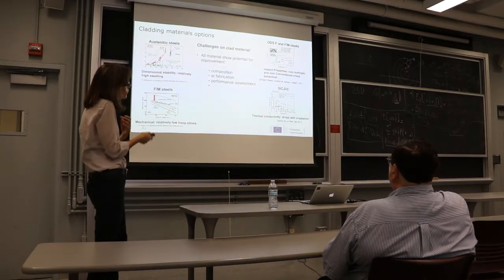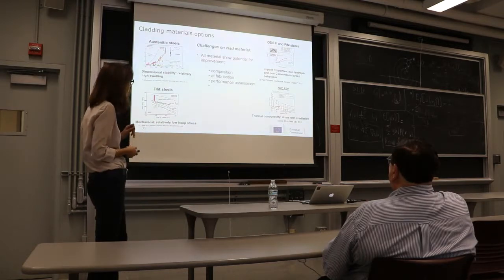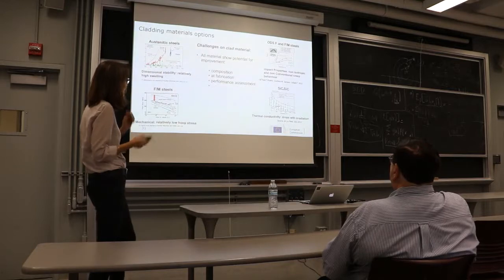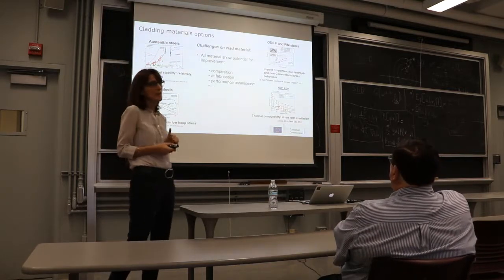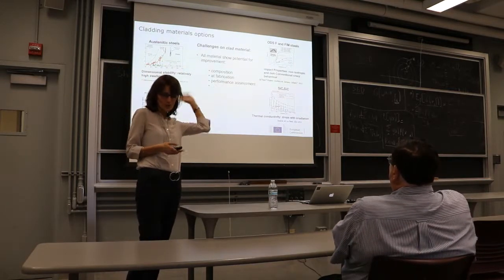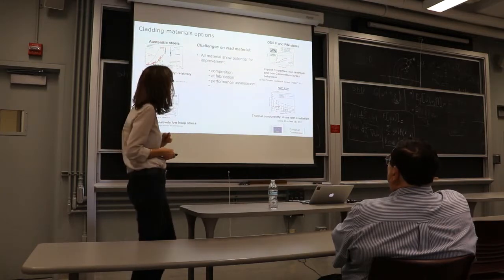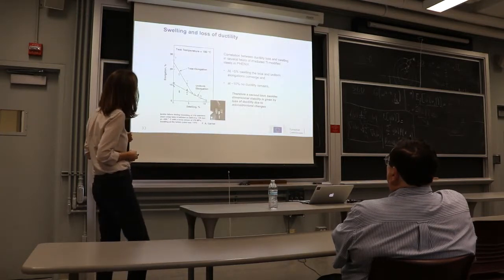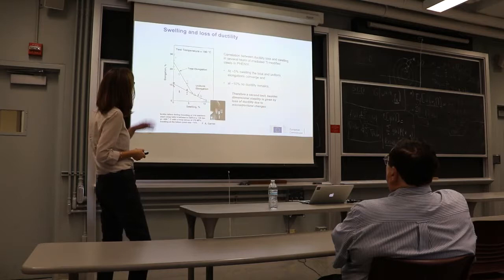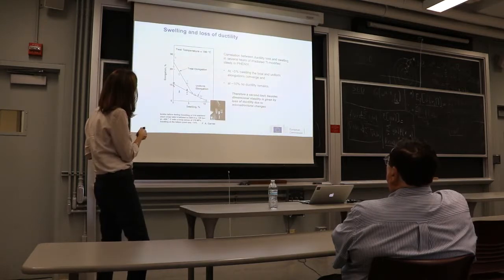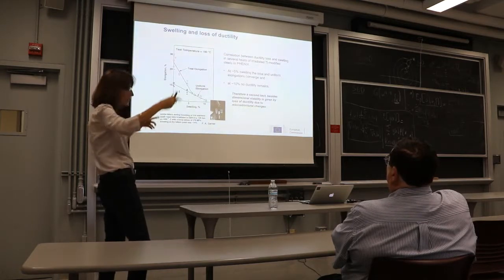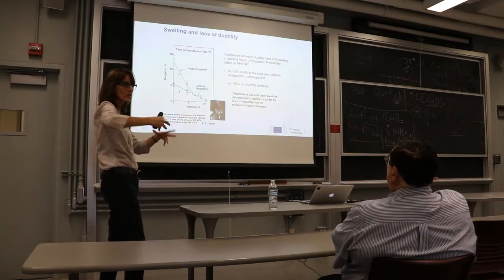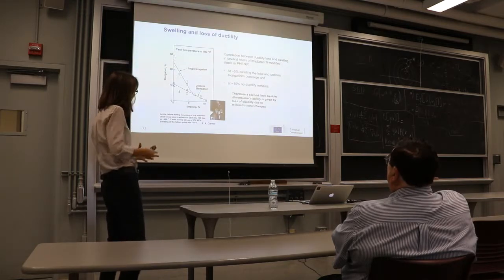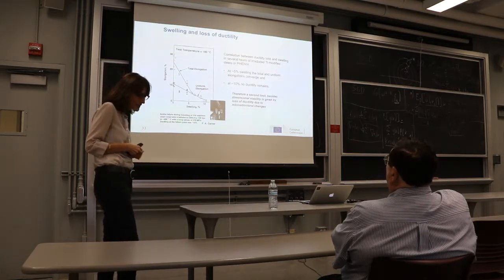So even if this is something that we know more or less also from the zircaloy, and in case of SiC-SiC is the drop of thermal conductivity with irradiation. So here all these materials have problems. Maybe just to enter, for the austenitic steel is the swelling, I told you before, so it's similar to the fuel. This material increases in dimension.